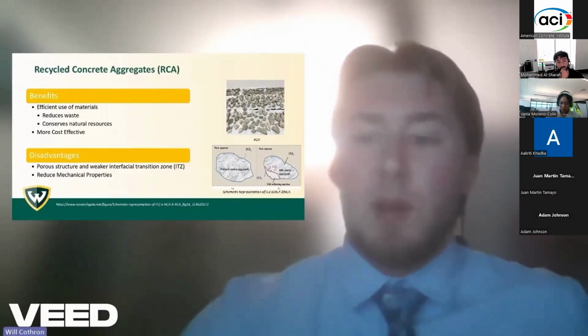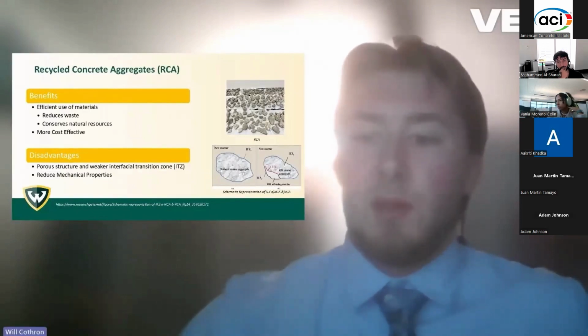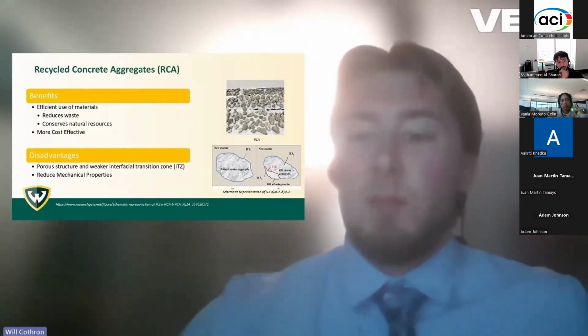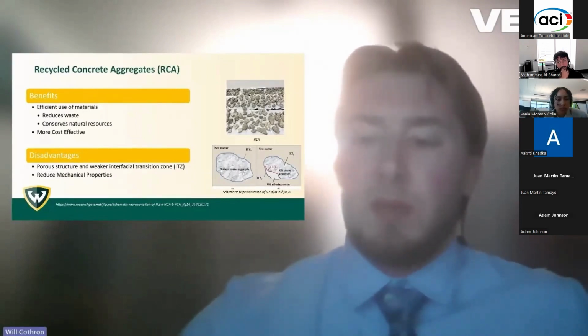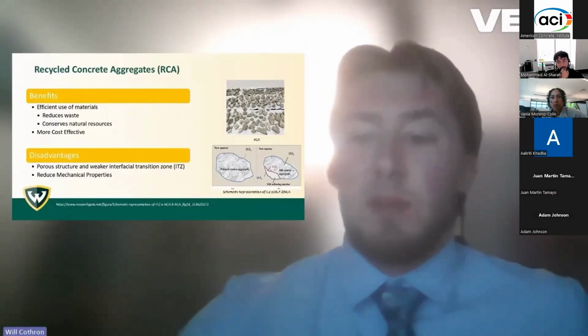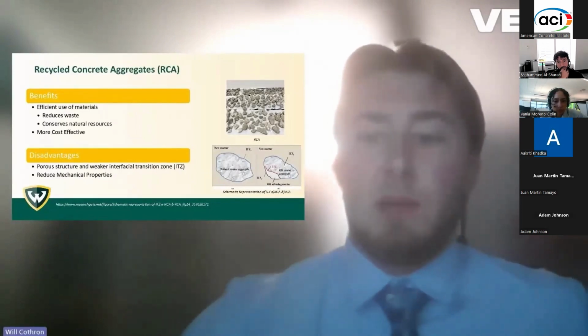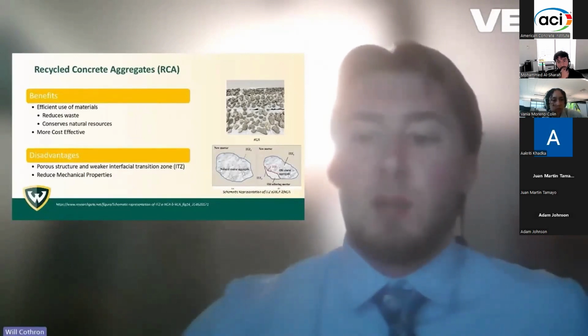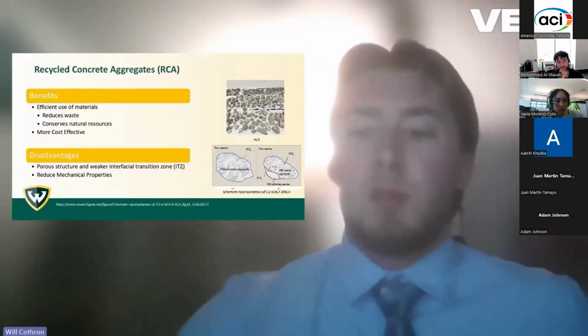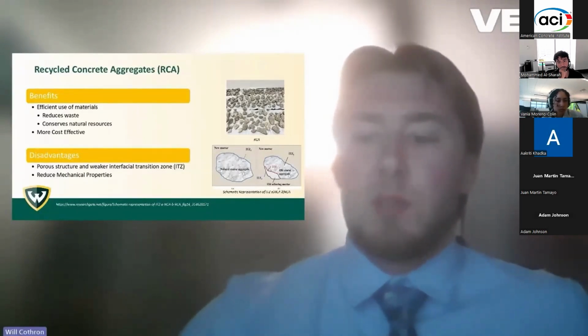Unlike natural aggregates, RCAs contain a double ITZ layer, the old ITZ between the original natural aggregate and the adhered mortar, and the new ITZ between the adhered mortar and the fresh cement paste. The adhered mortar within this new ITZ layer contributes to increased porosity, allowing greater water absorption and altering the overall water to cement ratio. This results in a weaker microstructure with poorer bonding between particles, ultimately leading to reduced strength and durability in RCA concrete.